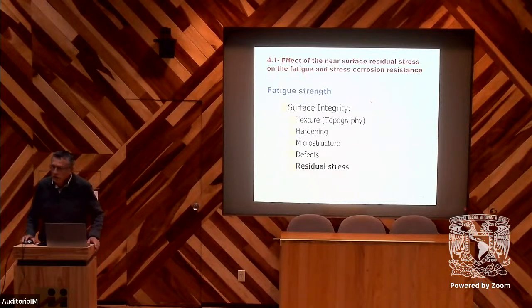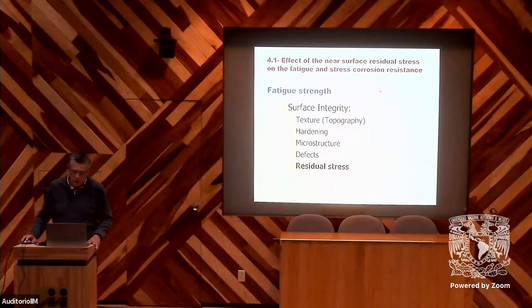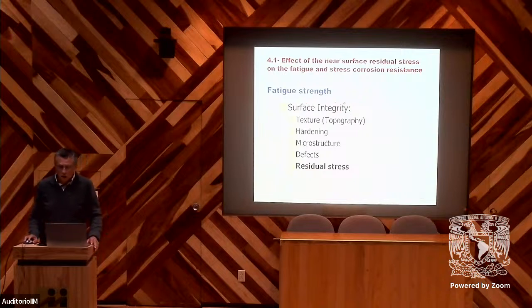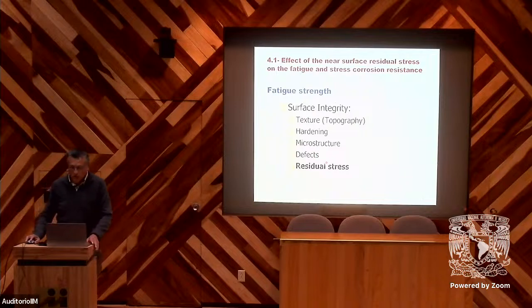So concerning the effect of residual stress on fatigue, we know that the fatigue strength of the material depends strongly on the surface integrity. What does surface integrity mean? It contains the geometry of the surface, the topography, the surface texture, the hardening, the microstructure, the presence or not of defects, and the most sensitive parameter is the residual stresses.